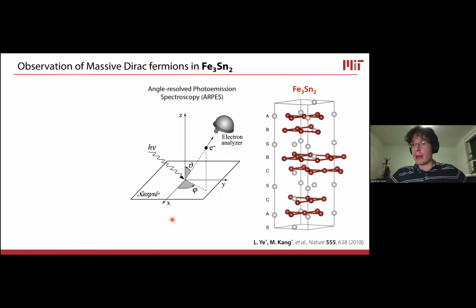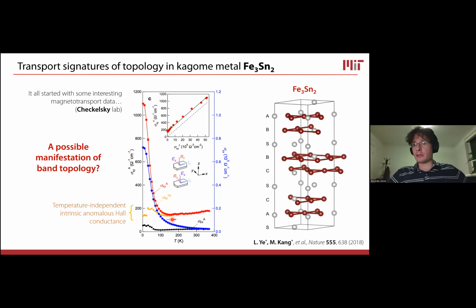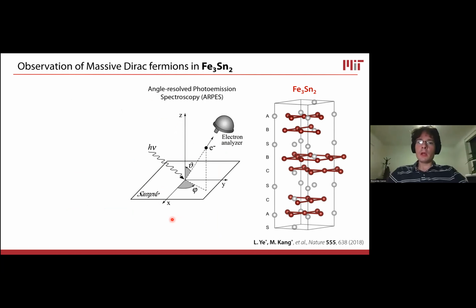This system is also a magnet, mind you. So this is why you see the anomalous Hall transport, and this is key to what I'm going to tell you about. So this is a system that breaks time reversal symmetry, has predominantly out of plane magnetization. So we looked at these systems using angle-resolved photoemission spectroscopy, which I will not discuss in detail.